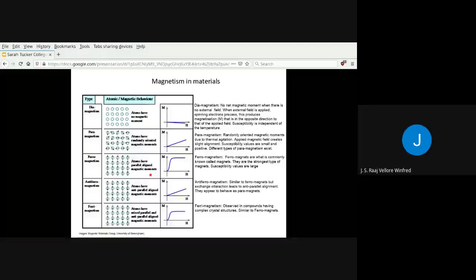There is also another one, which is antiferromagnetism. In the case of antiferromagnetism, it's very similar to ferromagnets, but their magnetic moments are not all aligned parallel to each other because of the interactions between the neighboring atoms. So this would result in anti-parallel alignment of magnetic moments. And sometimes they also appear to behave as paramagnets. The reason you would say that is because your M over H behavior for paramagnetic and antiferromagnetic materials is very similar.